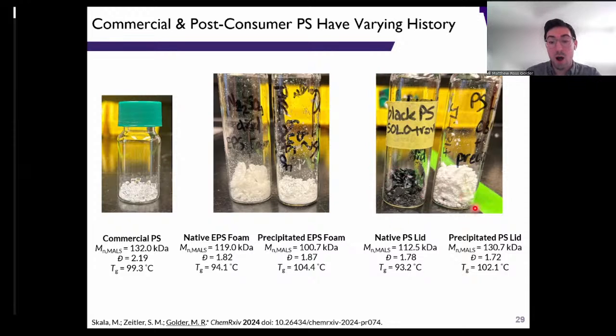the right. What you'll notice here, there's a small change in molar mass after we precipitate the material, and that's just due to the fact that we're artificially enriching either the higher or lower molecular weight region after precipitation, just depending on the particular conditions that we use. But perhaps more importantly, we see about a 10-degree decrease in glass transition temperature from a little bit above 100 down to about 90 to 95.